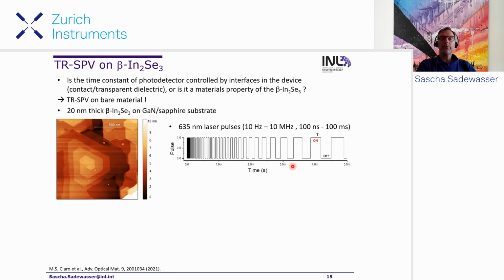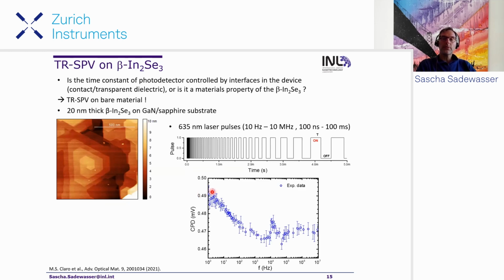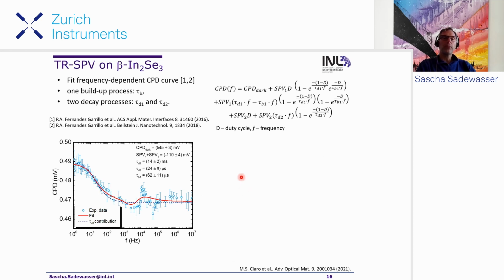And then again, we use our pulse sequence, here from 100 nanoseconds to 100 milliseconds. And this is the spectrum we see as a function of the frequency. So we have the decay here in the range of milliseconds. Following the previous work of Benjamin Grevin's group, we fit this dependence with this rather complicated looking equation, but in the end, it's just the dark value. Then we have two processes for surface photovoltage: one build up and two decays. So these are all characterized by these time constants.